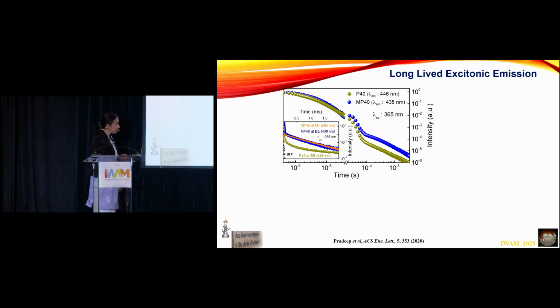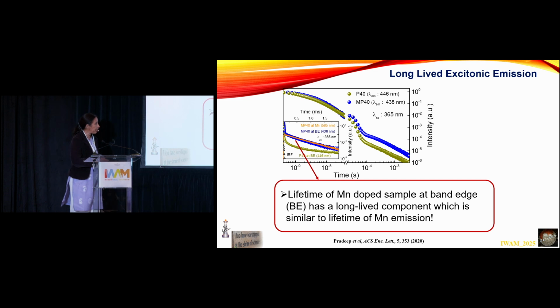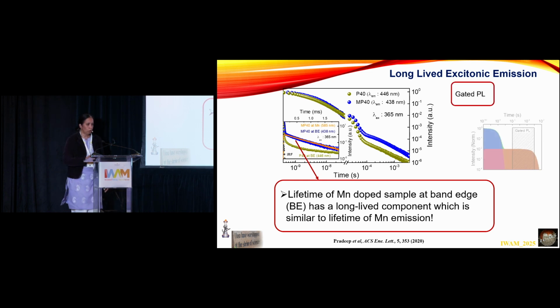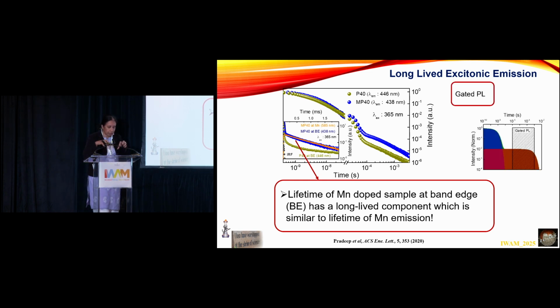And this is the excitonic emission, this is not the manganese emission. The orange one is the manganese emission, and the blue one is the excitonic emission. So the lifetime of the manganese-doped sample at the band edge has a very long-lived component. It's very small, there is a component which is decaying very fast, but there is this long-lived component, and that matches exactly with the lifetime of the manganese. So we said, okay, since it's very small and it tends to get buried inside the fast component, let us look at the gated emission.